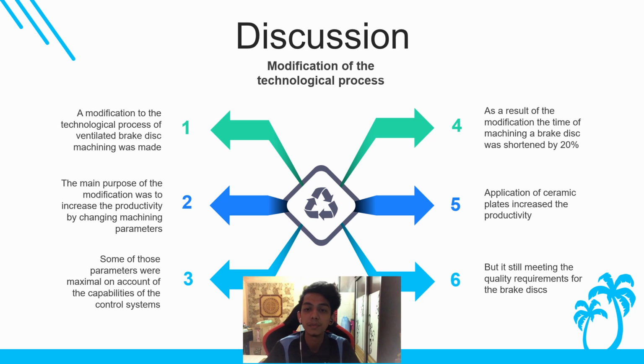As a result of the modification, the time of machining a brake disc was shortened by 20% on average. The application of ceramic plates increased the productivity by reducing the frequency of replacement while meeting the quality requirement for the brake disc.